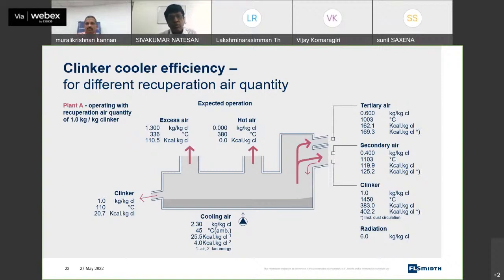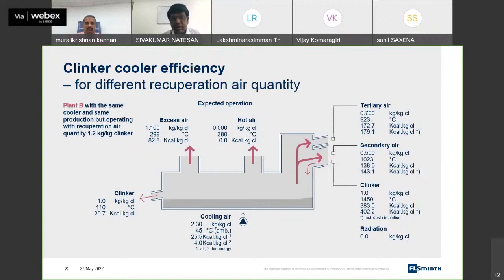So we will be able to take 110 excess air loss, and also clinker loss is close to 20. So these are the losses going out. But in the same cooler, if some process changes happen and we are trying to take more air from the cooler, the 1 kg we are showing here may improve to 1.1 or 1.2. We just redid the balance. If the quantity of secondary and tertiary air increases to 1.2, then you can see the drastic reduction in the excess air heat. But the cooler efficiency has not changed.